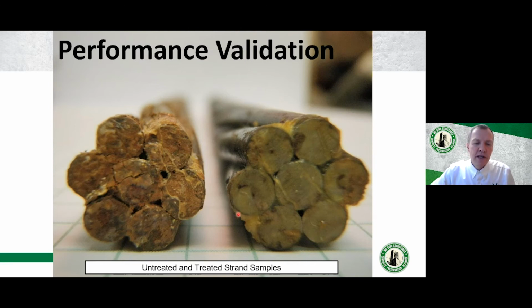This test was basically set up to simulate a piece of strand in a void where it's exposed to the impregnation material during the impregnation process, and then the material just is absorbed or leaks away, and will there be enough of a film there to provide protection? So I think visually that is showing some benefit there.